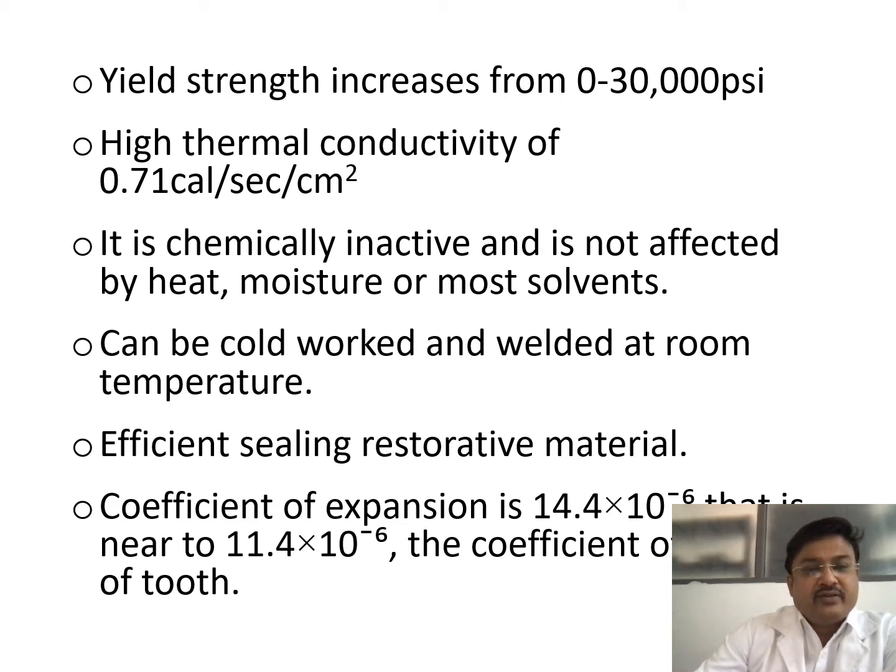It's got high thermal conductivity of 0.71 calories per second per centimeter square. It is chemically inactive and it is not affected by heat, moisture and most solvents. It can be cold worked and welded at room temperature. It's an efficient sealing restorative material. The coefficient of expansion is 14.4 times 10 to the power of minus 6, which is near to 11.4 times 10 to the power of minus 6, the coefficient of expansion of the tooth.